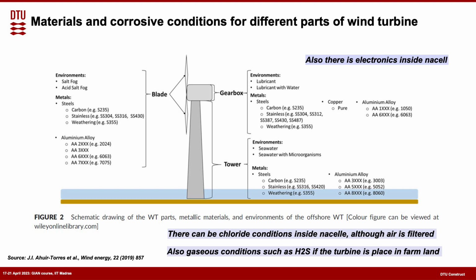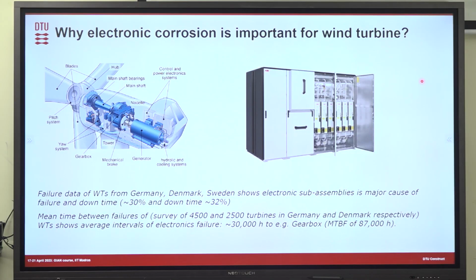But most of the time the problem with the humidity comes when the wind turbine is not working. That means this wind turbine can be shut down for 2 to 3 months for repair work, and then the humidity inside the nacelle will be very high, and that's the time most of the corrosion is taking place. So if you take the